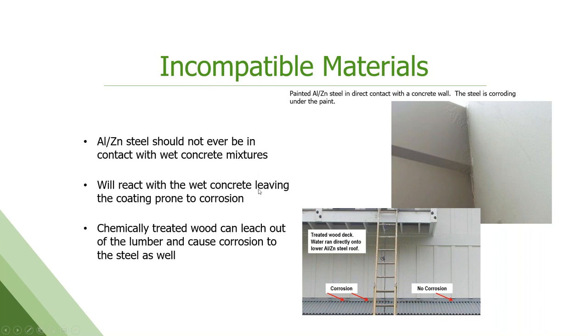The other things that are problematic out there is direct contact with concrete. You got to have a water vapor barrier in there because you'll get moisture from the concrete that leaches into the galvalume surface and causes corrosion underneath the paint. You can see here that this paint is starting to bubble up. This is the same house, by the way, that had the lighting fixture on the previous slide.